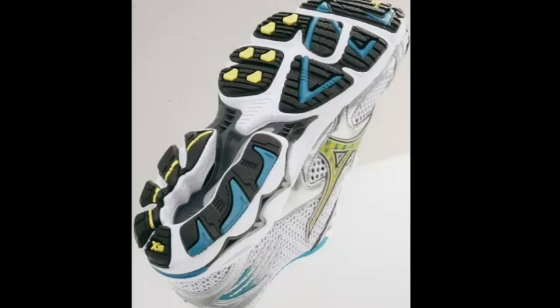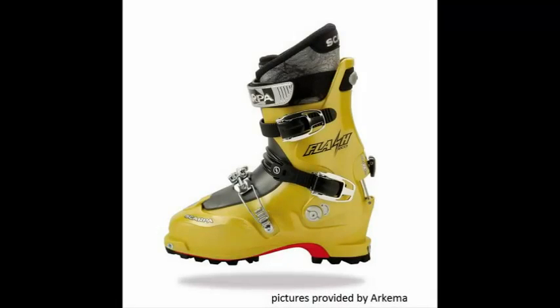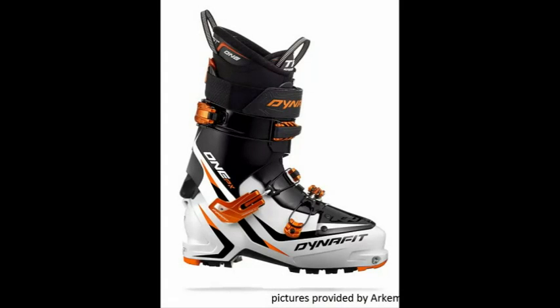Its unique combination of toughness, elasticity, lightweight, and flexibility allows the manufacture of soles that bring performance, comfort, and precision to sports footwear. On the market for over 30 years, constantly renewed and improved, Pebax is a high-performance thermoplastic elastomer featuring a unique array of sought-after properties: lightweight, energy return, flexibility, elasticity, fatigue resistance, impact resistance. All customized and fine-tuned by changing the ratio of its two components, polyamide blocks, for rigidity, and polyether blocks, for flexibility.